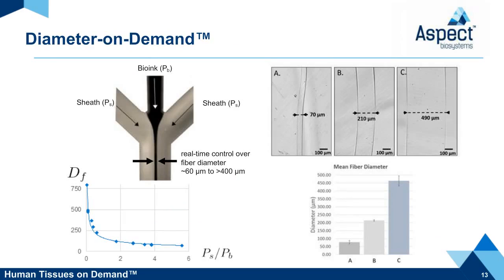The Diameter-on-Demand technology enables precise control over fiber size. On the left is a close-up image of the focusing intersection between the biomaterial and the cross-linker sheath fluid. By changing the pressure ratios of the sheath fluid and the bioink, we can modulate fiber diameter and even do this on the fly within a printed structure, as shown in the image on the right, where fiber diameter is increasing, moving from left to right.